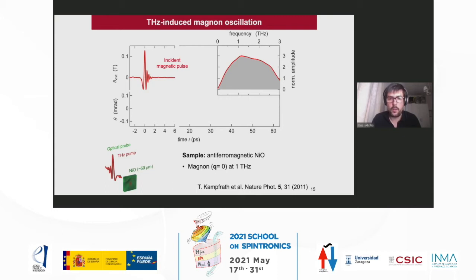This was a seminal work by the group of Tobias Kampfrat, a professor here at the University of Berlin. His group demonstrated that one can excite spin dynamics in an antiferromagnet, in this case nickel oxide, using a terahertz pump. What they did, as shown in the figure, is use an incident magnetic pulse of the order of 1 to 2 picoseconds. If you look at the frequency bandwidth, it's around 1 to 2 or even 3 terahertz.